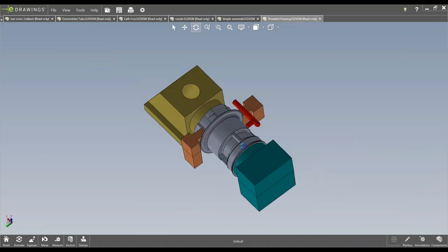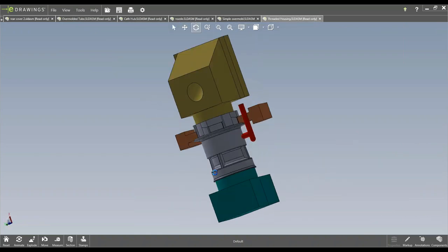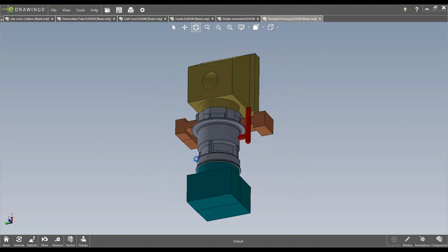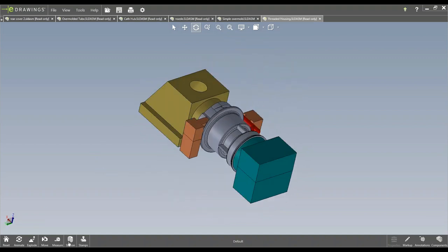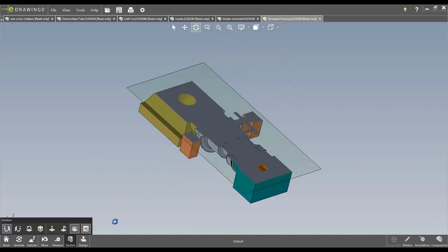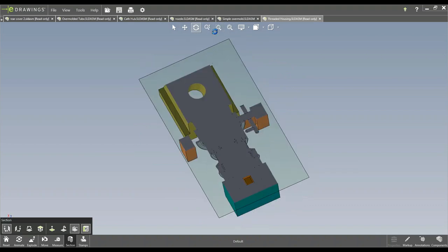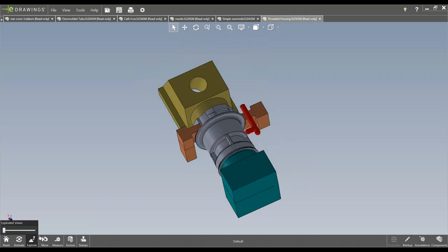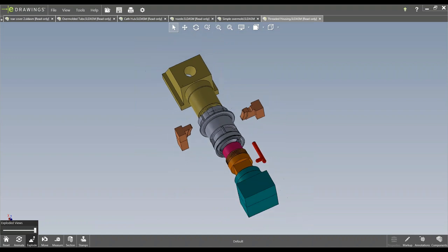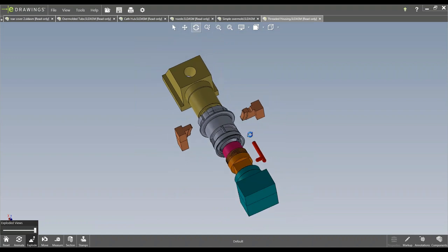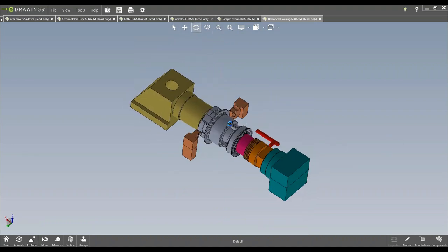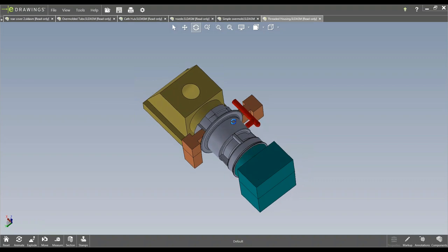I mean, this one, I don't think it really had much sink on it. It was cored out pretty well. I mean, we did have a thick area on the inside of the part here. Yeah, we do have a little bit of thick area. And I think we had a little bit on this one, but it's really going to come down to if it's acceptable on a part. We try to review that up front at the quote process, running mold flow analysis, identify thick areas or potential areas of sink, and then suggest changes to avoid that.